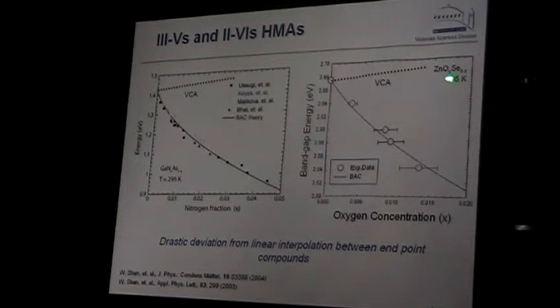The same is true with zinc selenide with oxygen. You put in a little bit of oxygen, and the band gap, instead of going up toward zinc sulfide, goes down drastically. So it means that this material behaves completely differently. A lot of work was done. This is an interesting property because under some circumstances, if you add a little bit of indium, you can have a material with a much smaller gap than gallium arsenide, but it could be lattice matched to gallium arsenide.